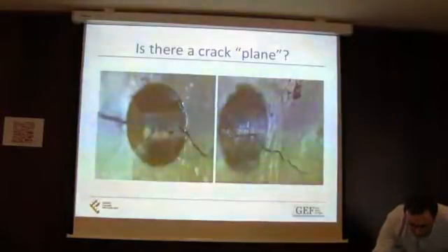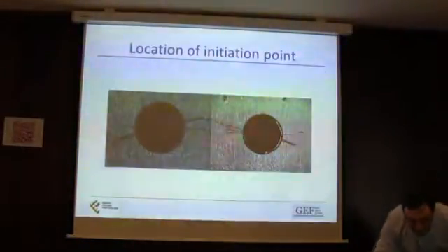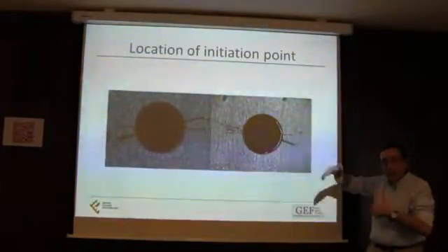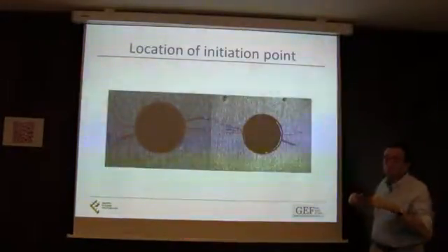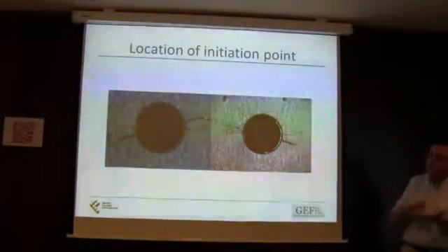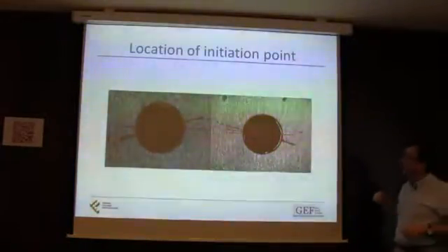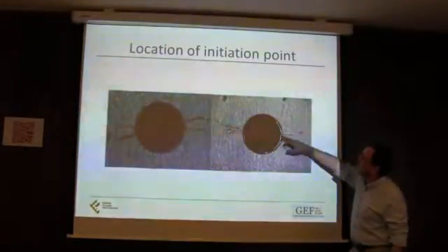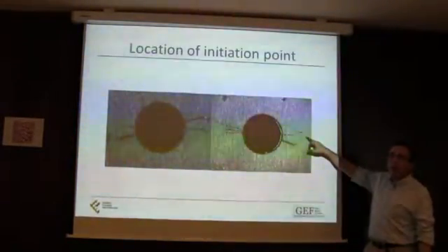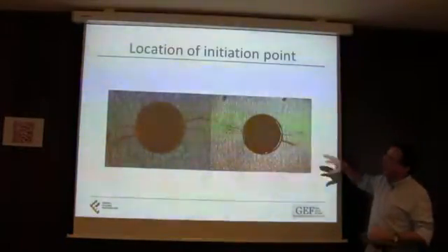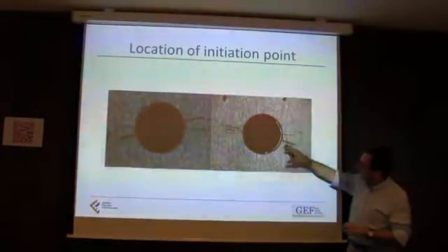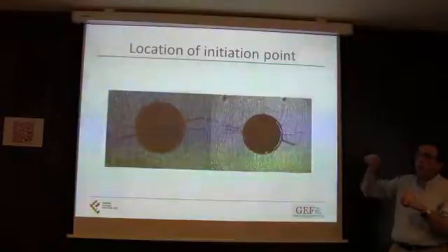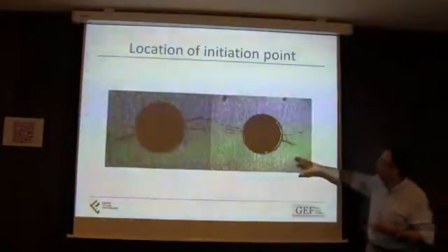Now, we did some investigations to see where the crack initiated. Although we know that we don't have a single crack plane, as I said before, some of the things that we were studying with our short crack models applied to notches tell us that we should not expect that the crack will always start in the plane of maximum load. We found out with our models that the size of the hole compared with the microstructure has something to say about where the crack will be initiated. So we were investigating that here.